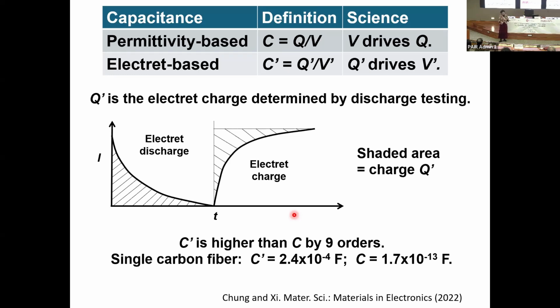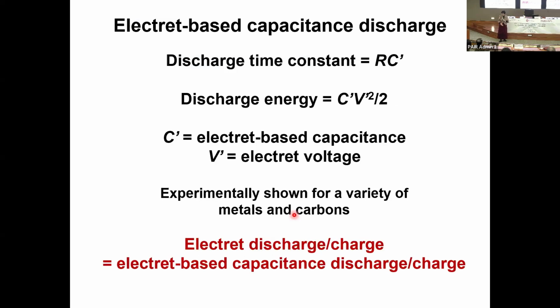You might wonder, well, what's so great about this quantity? Was it just dreamed up? Well, it matches experimental results. For the usual capacitance, the discharge time constant is RC, right? RC time constant. The discharge energy is half CV squared. In this case, the discharge time constant is RC prime. The discharge energy is half C prime V prime squared. And this has been experimentally shown for a variety of metals and carbons. This means the electret discharge and charge simply boils down to the electret-based capacitance discharge and charge.